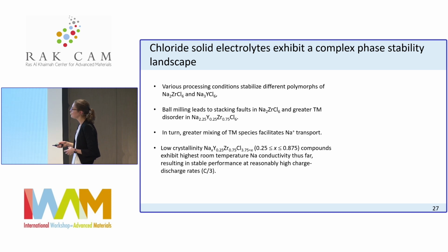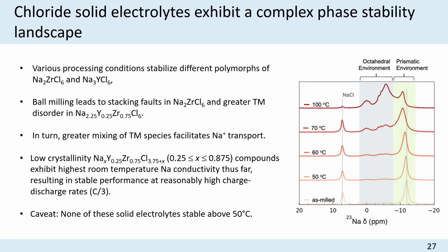And what I haven't shown you is that we tested these materials in all solid state batteries, and they perform reasonably well at a rate of C/3. So here you're charging and discharging in about 20 minutes. The caveat is that these solid electrolytes are not very stable. And so you can clearly see this. This is for one of these. This is the best low crystallinity material that we found here.